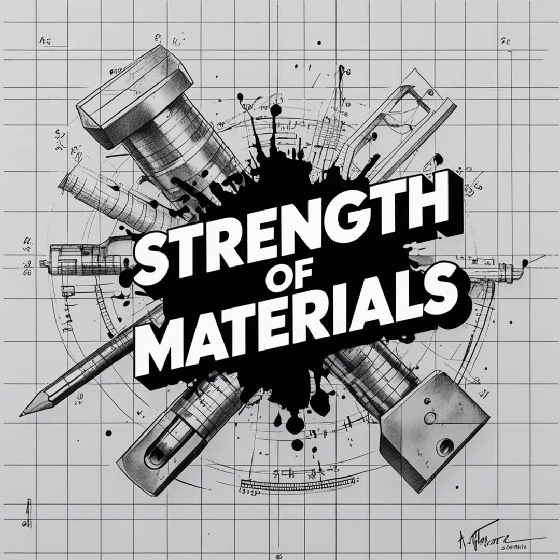Alloy composition. What are we actually mixing into the steel in the foundry? Let's stick with our plain carbon steel example. Increasing the concentration of carbon in the steel increases the transition temperature. It makes it more brittle. Okay, why does adding carbon do that? The reason is purely mechanical. Carbon atoms are what we call interstitial, meaning they don't replace iron atoms in the grid. They sit in the empty spaces, the gaps, between the larger iron atoms.